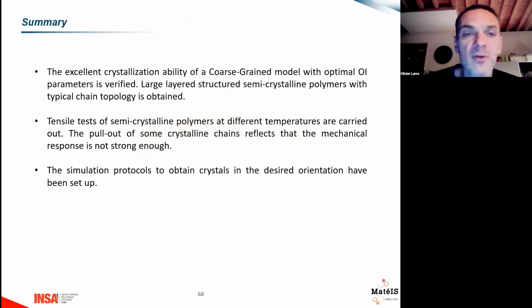So to sum up, we have built, after a very long time working on that, a model that represents the real systems realistically. We perform a tensile test. As I said, we have some problem of pull out of the crystal, and then the crystal is too weak. But anyway, we can use this system to test in the Z direction on an oriented system. We can finally test the amorphous phase and try to understand the mechanical properties in relation with the topology of the chain.